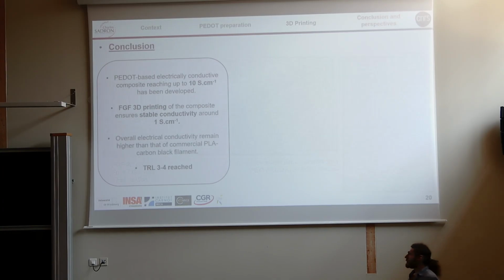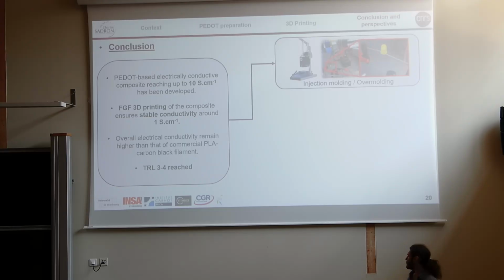So to conclude, I began working with a composite that exhibited conductivity values up to 10 Siemens per centimeter, and I proved that we could have stable conductivity up to 1 Siemens per centimeter using an FGF 3D printer, and this kind of conductivity remains higher than those of most commercially available equivalents.